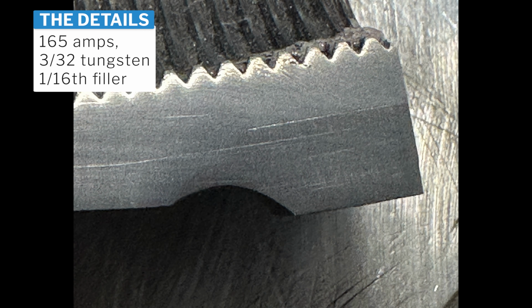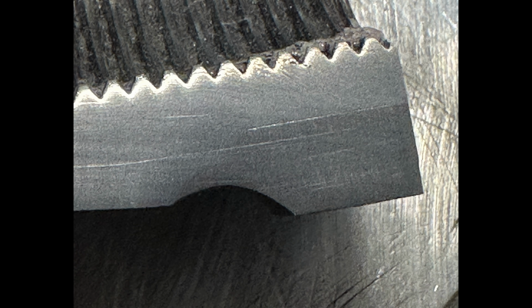So this is the first TIG weld I did where I ran just basically a root pass and didn't fill in or cap it. And what you see there is basically just underfill. To attempt to do that in a single pass with TIG, you'd need a 3/32 rod and likely a fair amount of amperage, probably up near 190, 200 amps. And that isn't generally what I do. So again, underfilled.